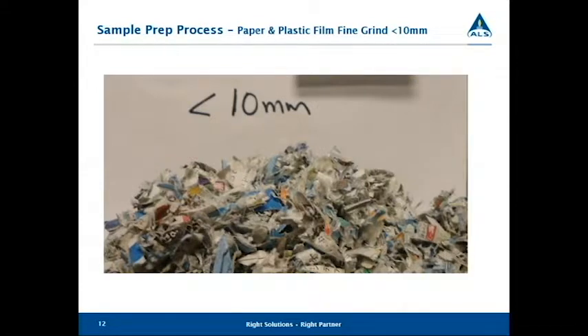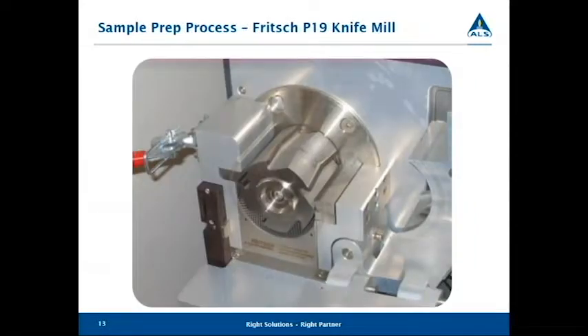So the next step that we do after we get the coarse grind is we go through a fine grind process, and we use another knife mill. This is the same manufacturer as the first one. It's a P19 mill, and this will take the material down to 1 to 2 millimeter in size.